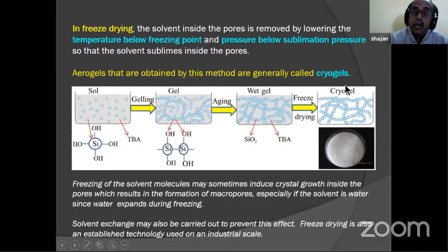Since it is being done at a very low temperature, this type of gels are usually referred to as cryogels also. But here you should be very careful, just as you take precautions when working at high temperatures. In freezing, you have to take precaution. Since you are going below the freezing point, sometimes crystal growth may occur inside the pores. Suppose the solvent is water, then you are coming to the 0 point, then freezing takes place. And if the crystal growth is